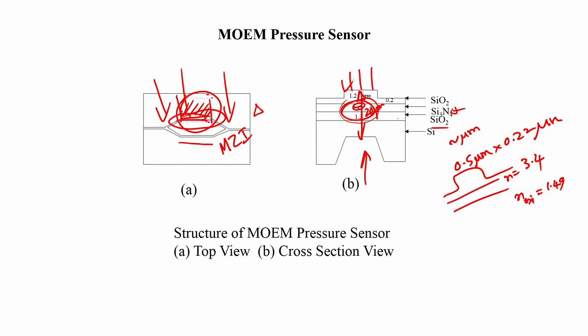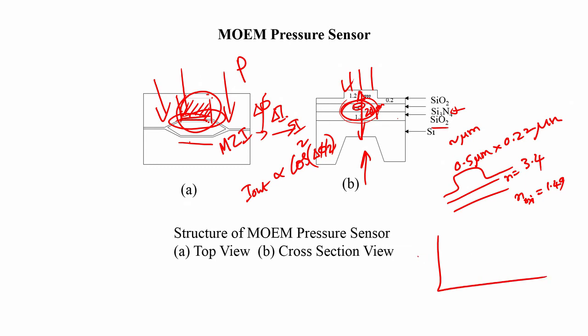There is a different phase variation between these two waveguides, which can be measured as a phase shift output at the end of the interferometer, which is converted into intensity change. So, the intensity output is dependent on the phase change at this point, typically cos square delta phi, like in other MZI structures. So, you can calibrate this device for pressure as a function of the light intensity output. Light intensity output with the pressure, typically, I will show a few pictures later on.